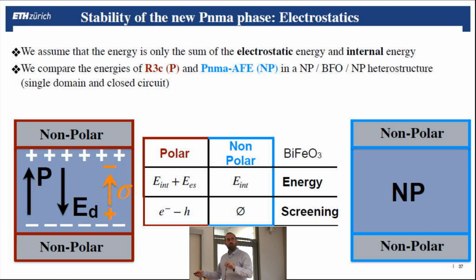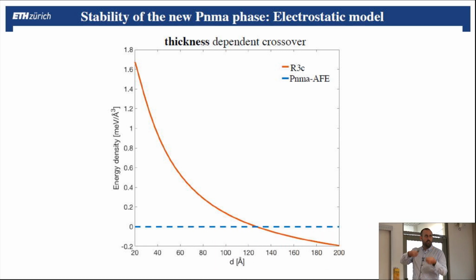So now we can compute this too. I will not show you what are the equations, and it's not so relevant for this. But what we can show is that if we compute now this energy for the polar case and this energy for the non-polar case as a function of the thickness of this bismuth ferrite layer, this is what we obtain. So here I'm plotting the energy density. So I divide by the volume, which is why you see in the non-polar case a line, because the internal energy scales with the volume, as it's only the internal energy.